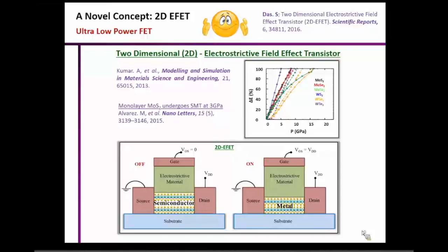So what is really happening is when you apply this out-of-plane pressure to these 2D materials, you essentially decrease the air gap between the consecutive layers, because there is an air gap which is holding these 2D materials together. And when you decrease this air gap, you are changing the overlap of the atomic orbitals, and that's changing the band gap.